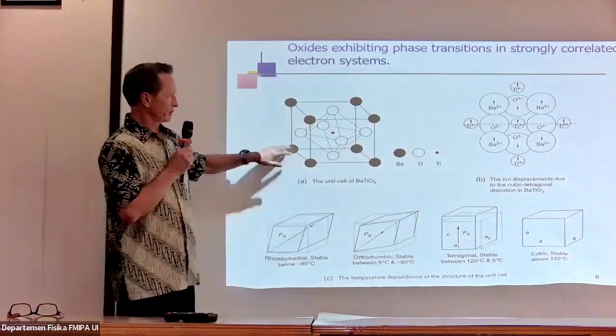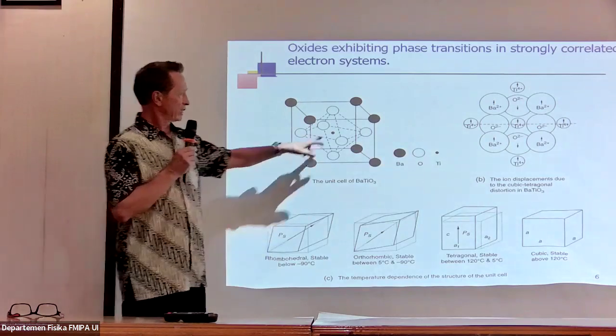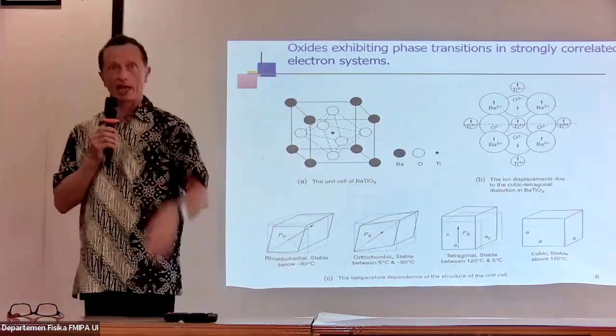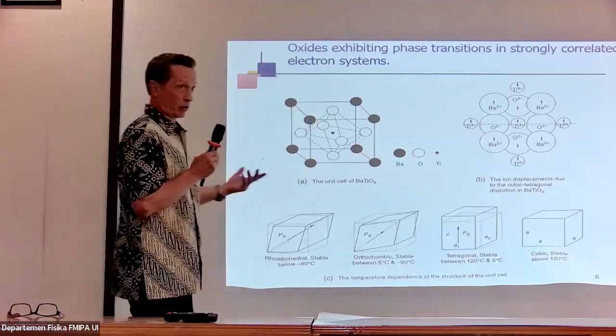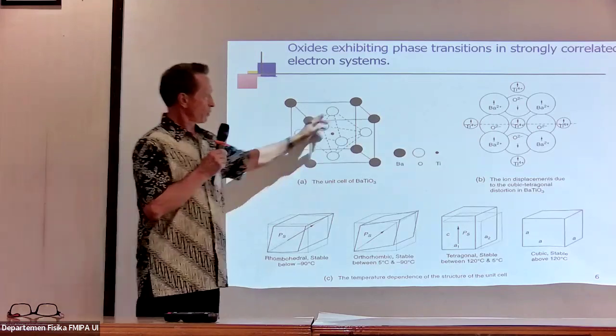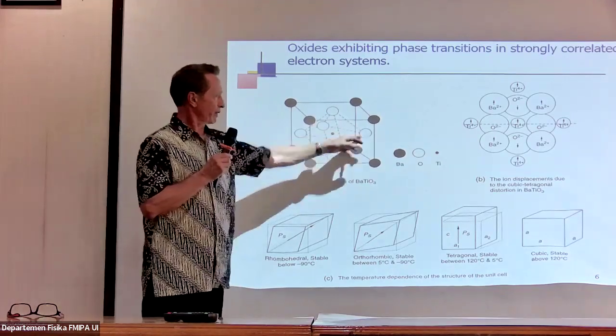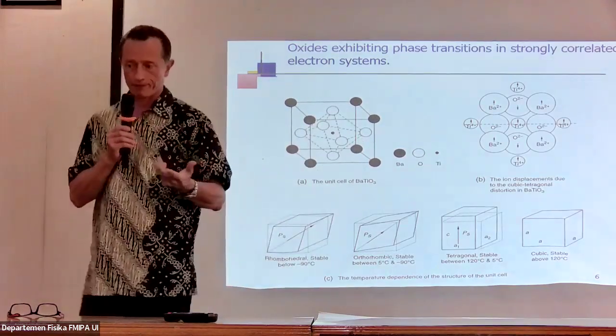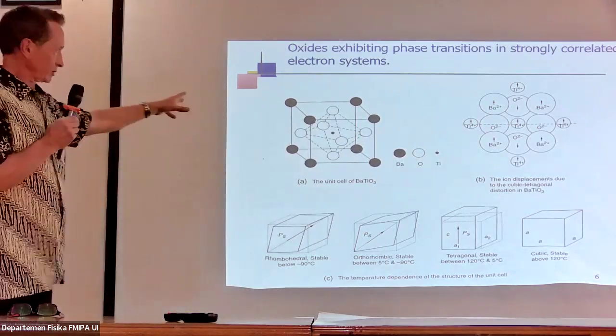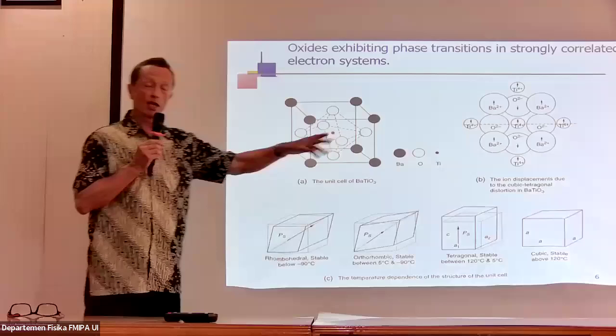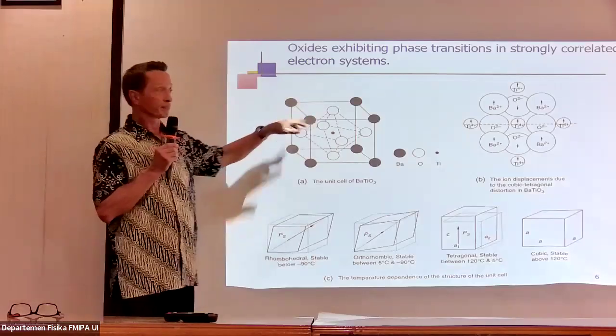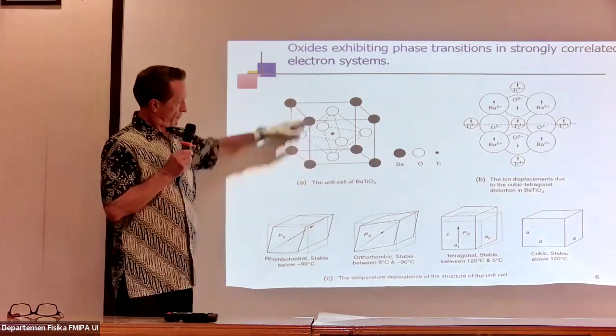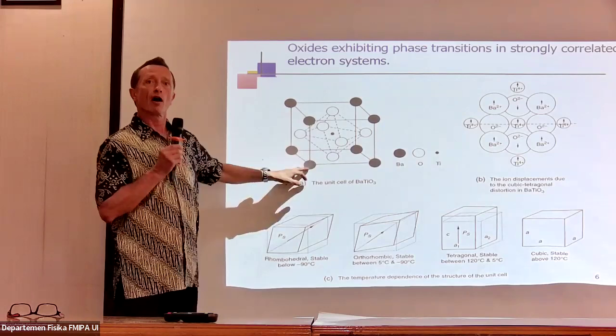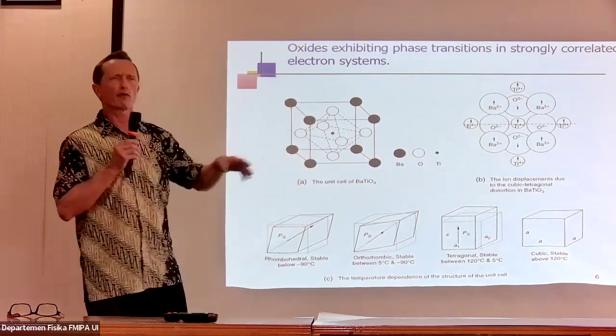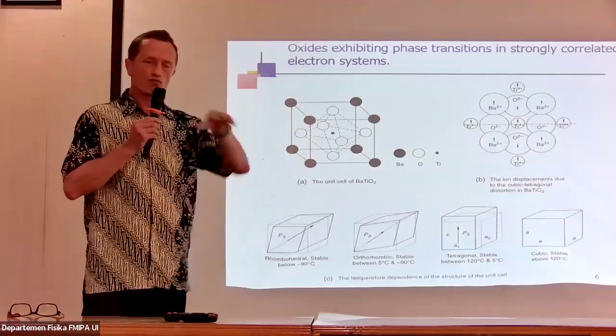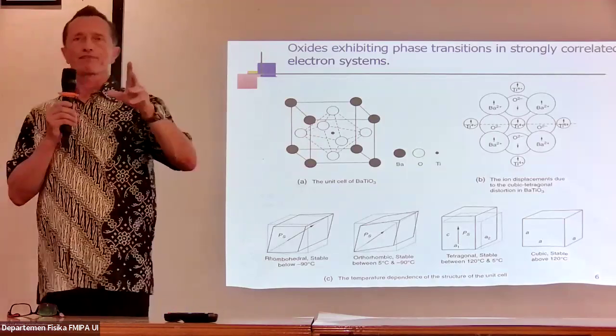So in this perovskite structure, in the corner, we have the barium, the big cation. And in the center, we have titanium, which is a small ion. So we have different polarity between these ions. And around the titanium, we have the famous oxygen octahedron. And this is here the perfect structure. After, when you develop your material, you will have some defects. That means sometimes, you imagine this length, that means one side of the pseudo cube, depending on the different atoms you use in your oxide, it's something close to 1 nanometer.